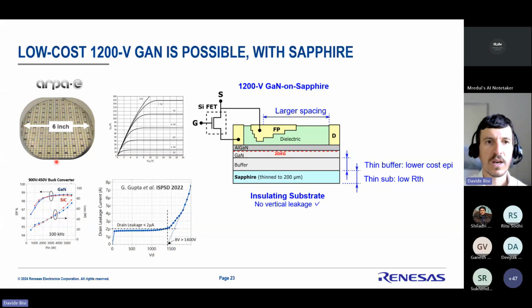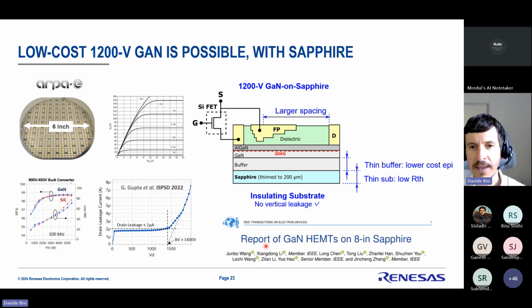You can see here a 6-inch wafer, again on sapphire. You can see now the leakage curve has the knee voltage at 1400 volts. So you can see that at 1200 volts, we're still in the flat region, very promising. And from the very first data points it's already competitive with silicon carbide. So this is just the first iteration. Now we're going through the next iteration to improve performance even more. And if you're worried about the wafer diameter, be aware that there's already a report in the literature about GaN HEMTs on 8-inch sapphire. So sapphire is future-proof, it can be scaled from 6 to 8-inch to further reduce the cost of manufacturing. So very exciting technology.